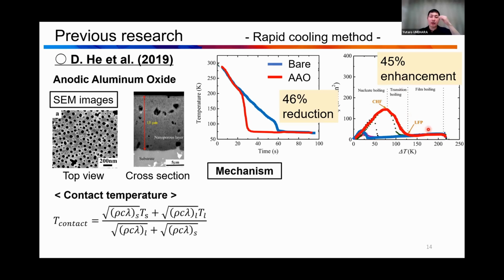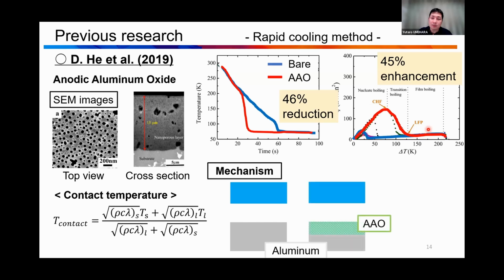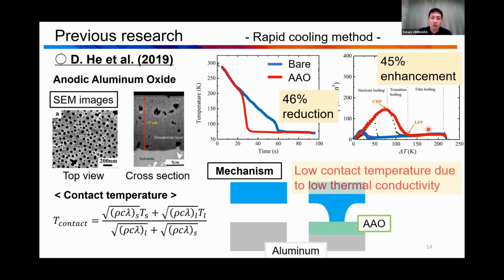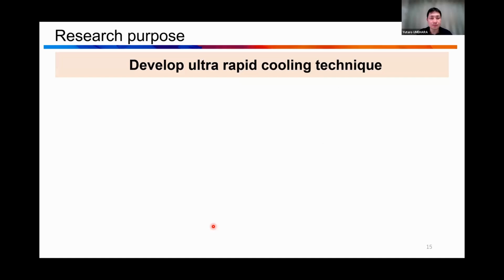So they reported that the mechanism is based on the contact temperature. Aluminum and the AAO surface are totally different in contact temperature, because AAO is a porous layer, so it has low thermal conductivity. Finally, they can get this kind of low contact temperature. So they reported this is the main mechanism of the rapid cooling.